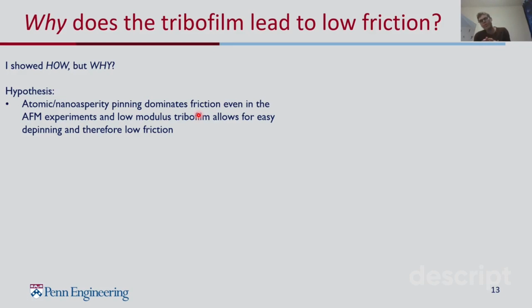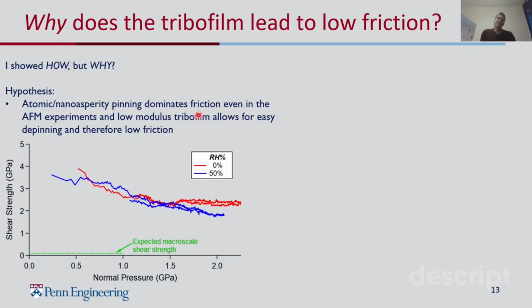And therefore, when we grow the tribofilm, we actually make one side of the interface very soft, and so that allows for easy depinning of the surface. And so that's how our friction is dropping. So why do we think this? Well, let's return to our nanoscale experiments for a moment.